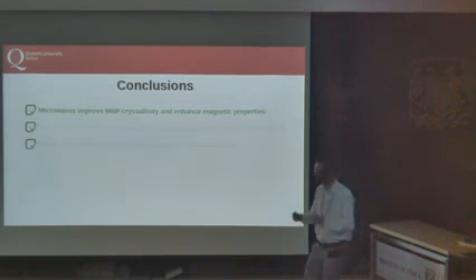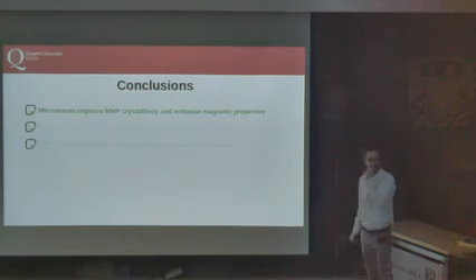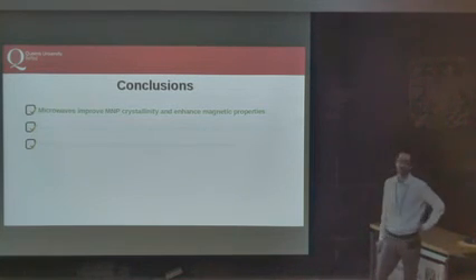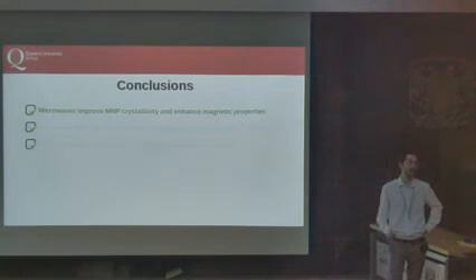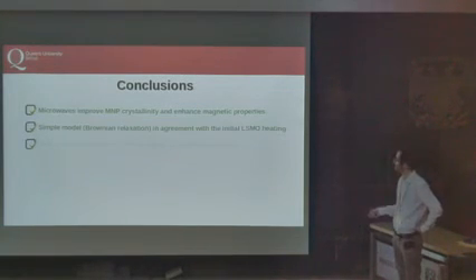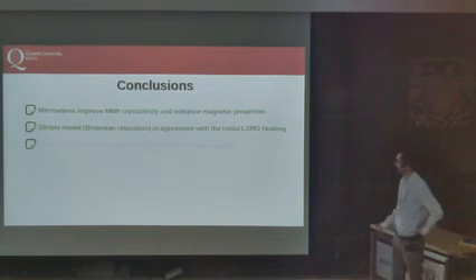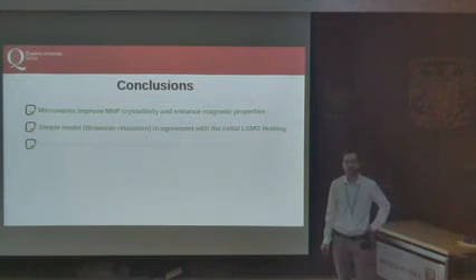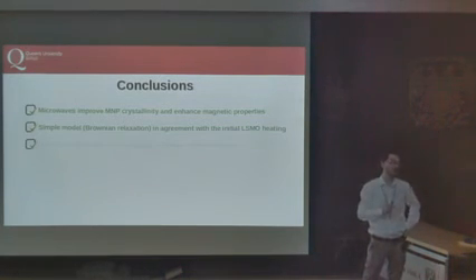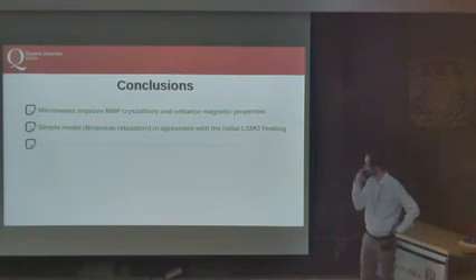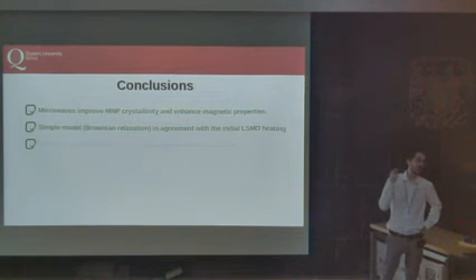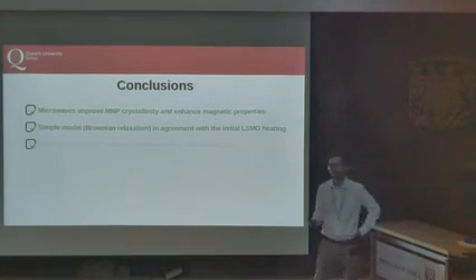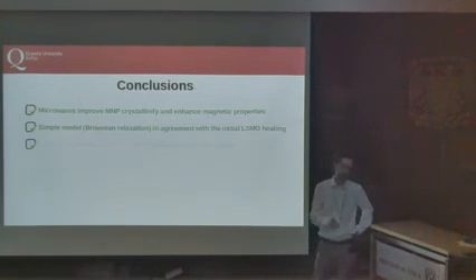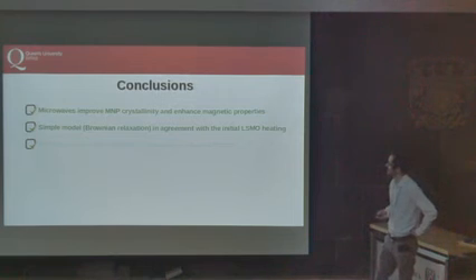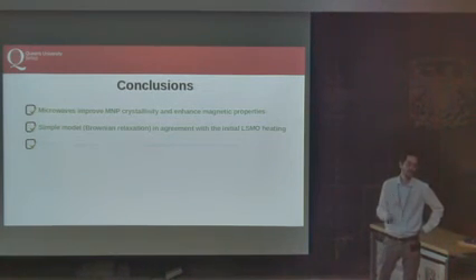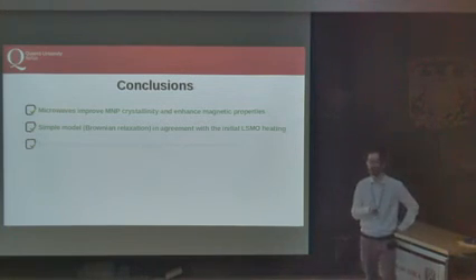Conclusions. Sorry for the long talk. From the experimental part, microwaves improve the crystallinity and enhance the magnetic properties. In fact, they are very close to the ideal value. The simple Brownian model, where we don't have Néel relaxation, is in this case very close to the initial part of the heating curve, the initial heating. I don't want to say that this is an explanation, because there are too many things that we don't have under perfect control, including experimental values. But it's encouraging in the sense that this theory can be used, perhaps adjusted for the aggregation.